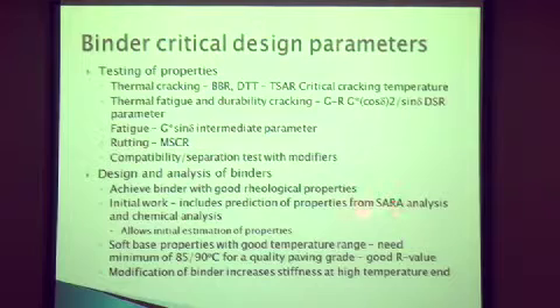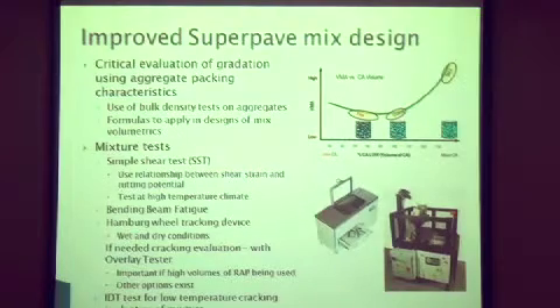You can do work with chemical analysis, things like the SARA analysis. SARA is really an automatic Corbett analysis. Put your binder into asphaltenes, resins, your saturates and your naphthenic aromatics. You can get initial estimation of the properties from that analysis. Ideally, you want a soft base with a good R-value. Modification of the binder can increase that stiffness at the high temperature end very well.